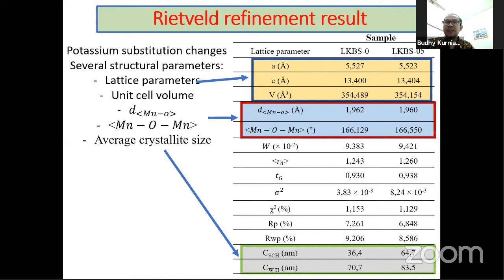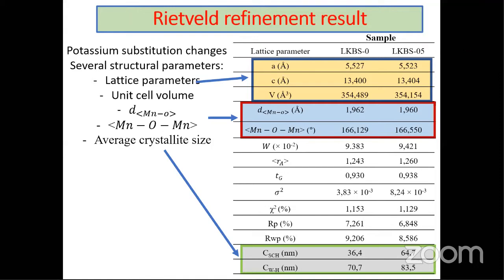And this is the Rietveld refinement result. Since the crystal structure is not changed, only some of the structural parameters are slightly different, for example the unit cell volume, the manganese-oxygen length, the angle of Mn-O-Mn, and the average crystallite size. From this calculation, we find that the crystallite size becomes larger when we substitute potassium. Next, please.